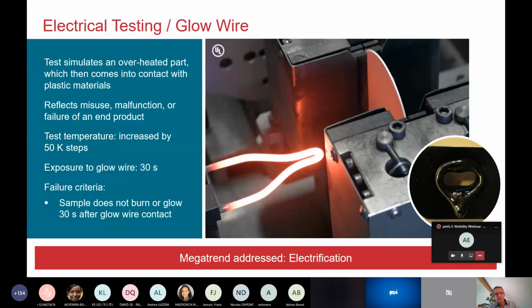This side here is the glow wire test, which is a very important test to simulate malfunctioning electrical components. Compared to the flammability tests with open flame, here you have an energy source, a glowing wire. The principle is that the glowing wire penetrates your material, you get in touch, and you look at how the material behaves. You do that in different steps, 50 Kelvin steps, and then you classify the material accordingly.